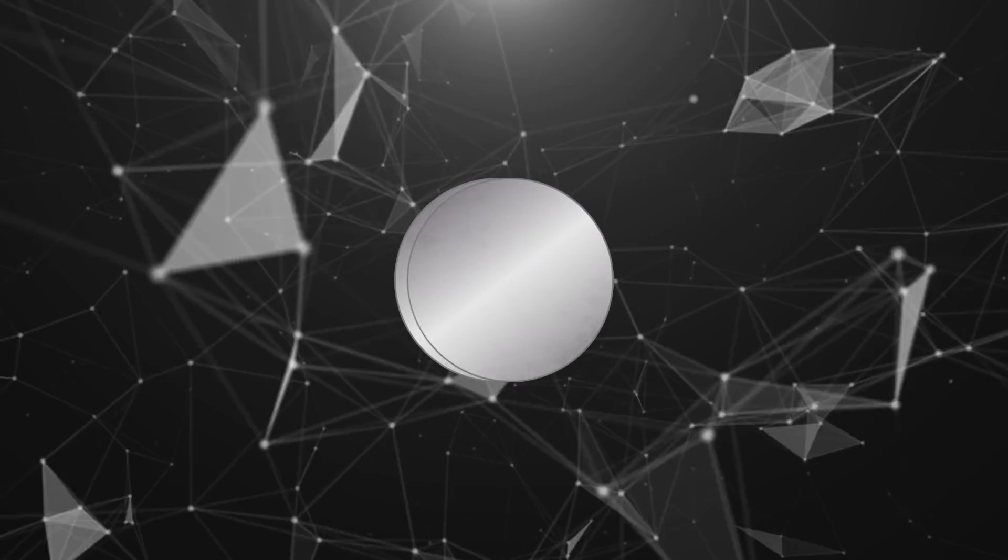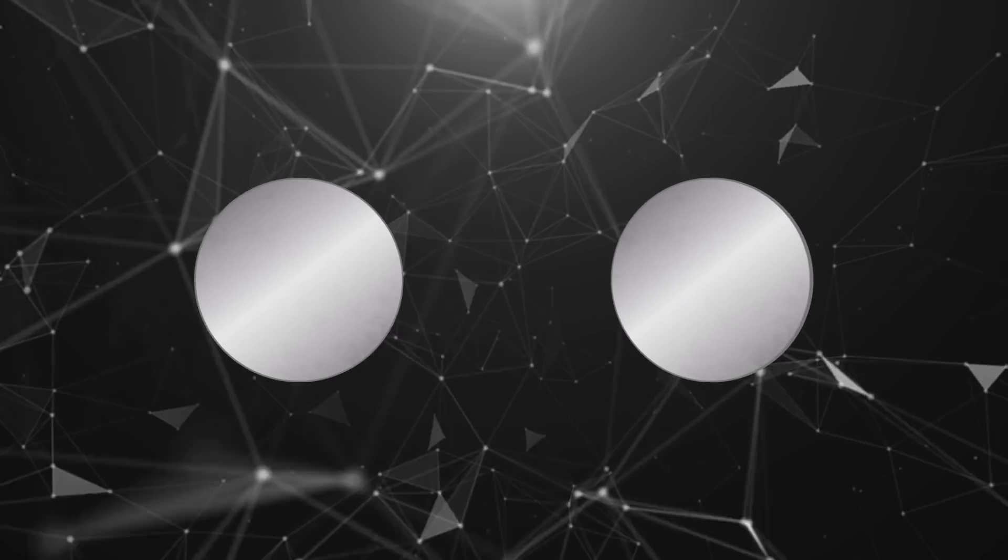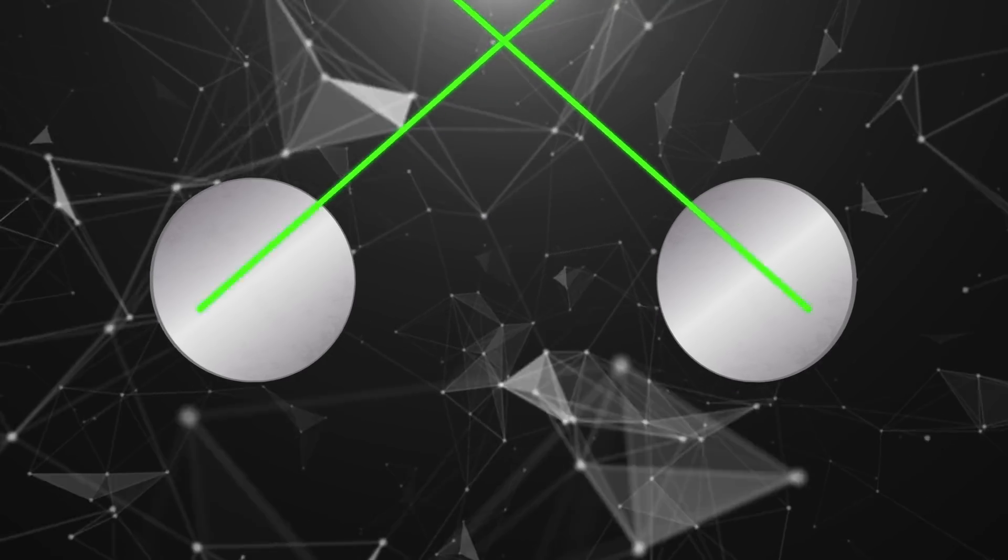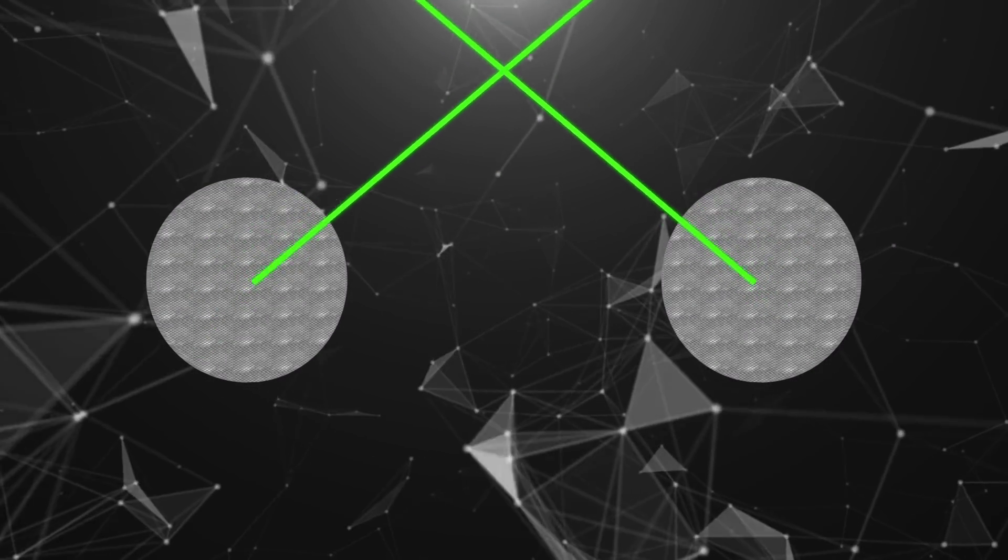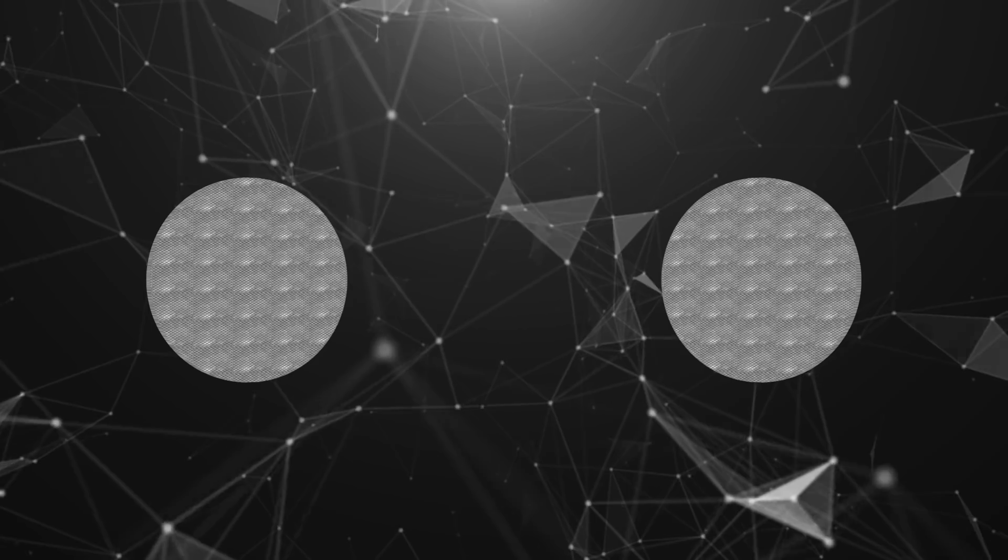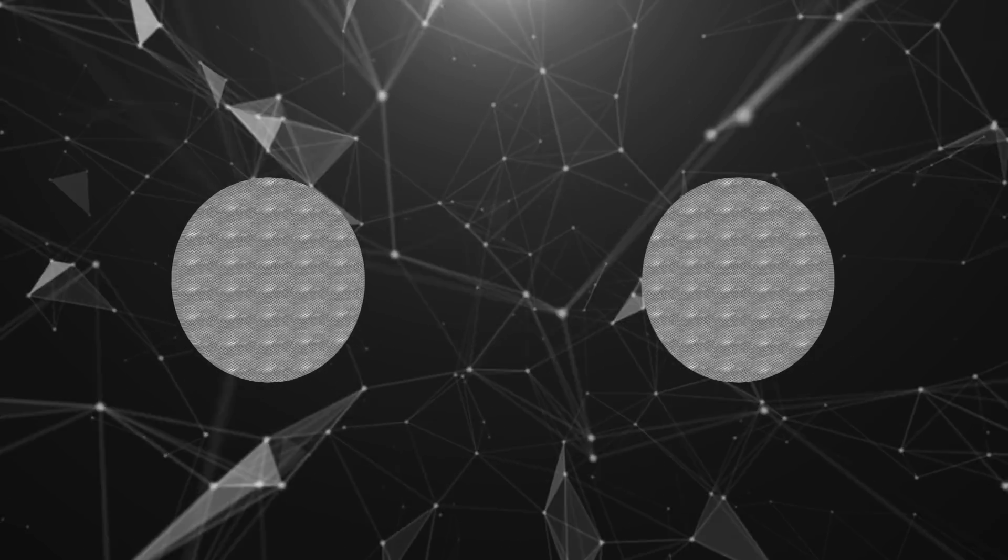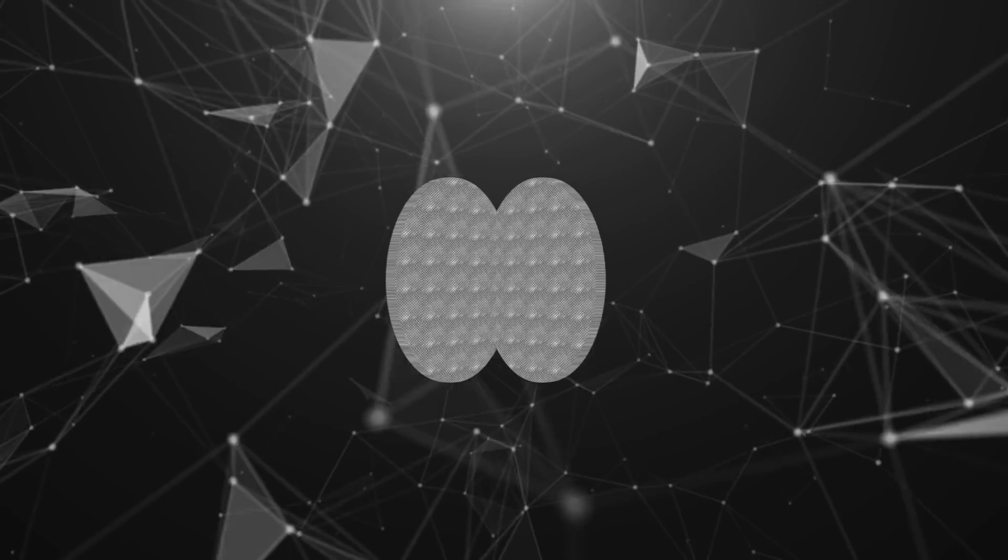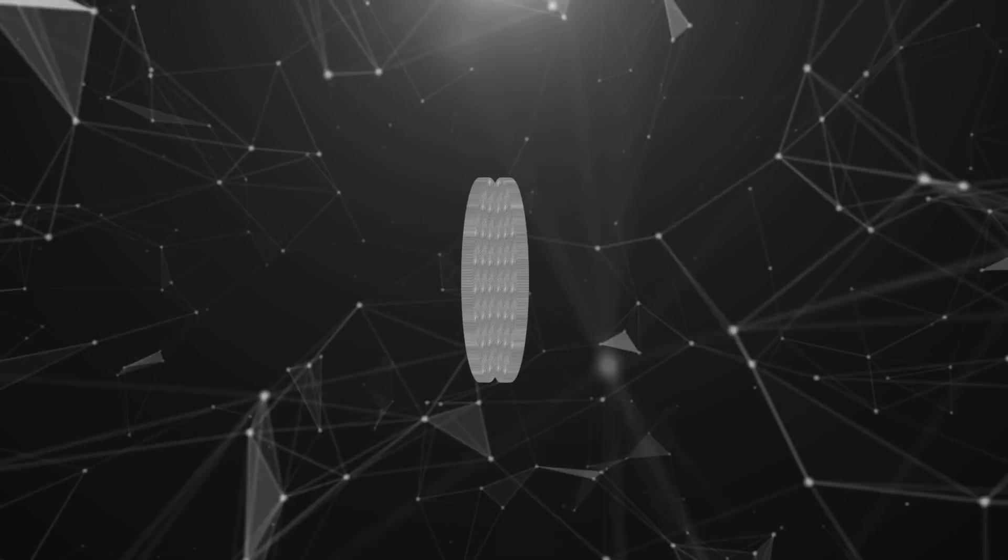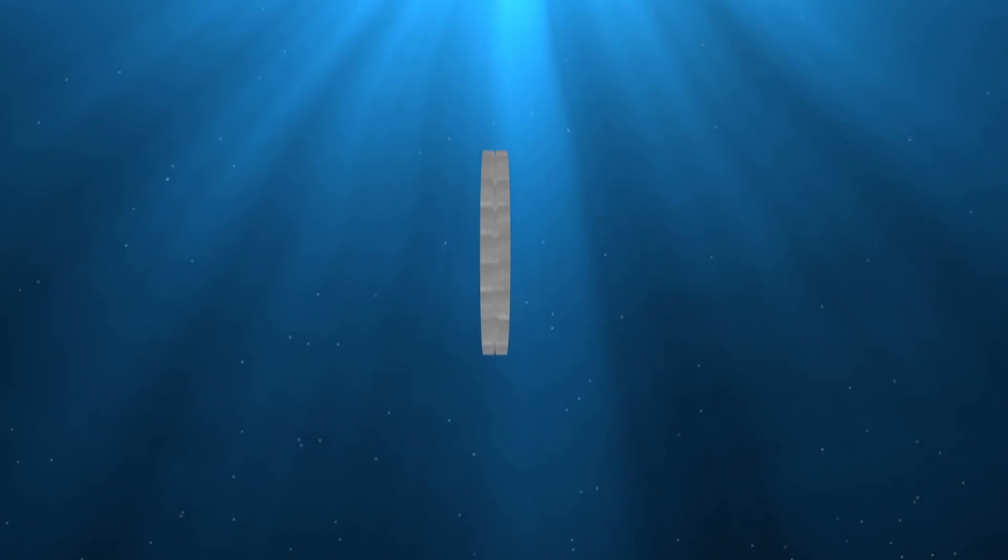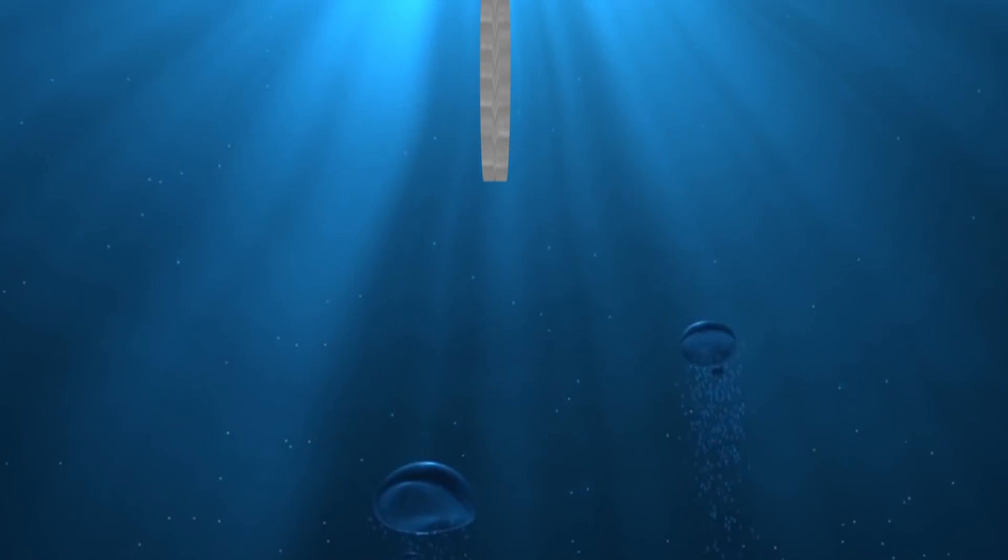As a result, the team of scientists created a design in which two metal plates were covered with tiny patterns, just like in the previous experiment, and then they were placed on top of each other, with the pattern on the inside. There was enough space between the plates to capture and hold air, which prevented the metal from sinking.